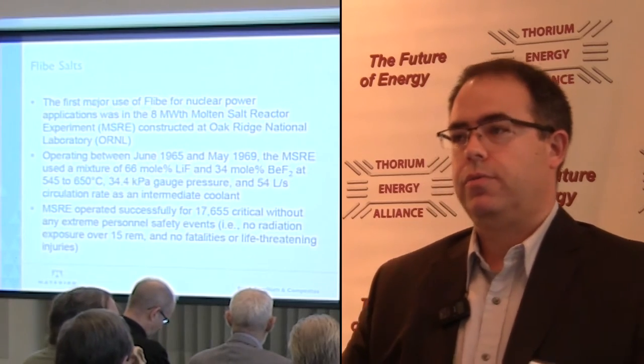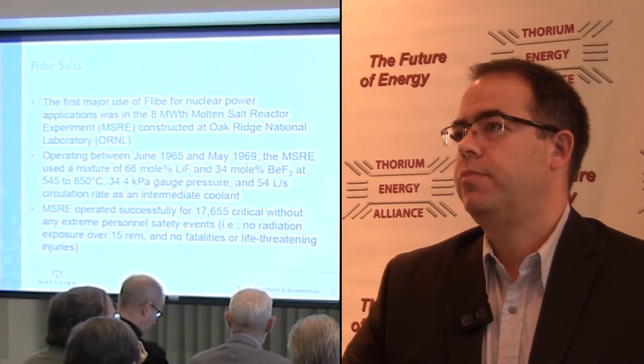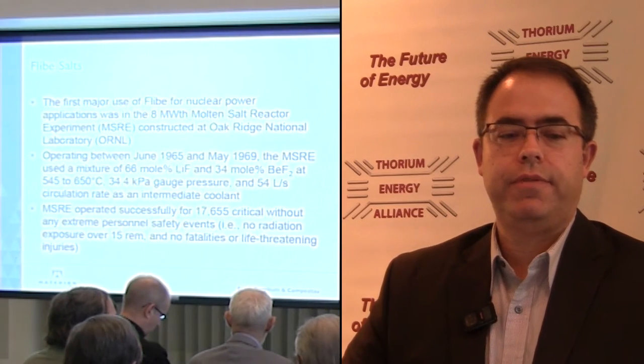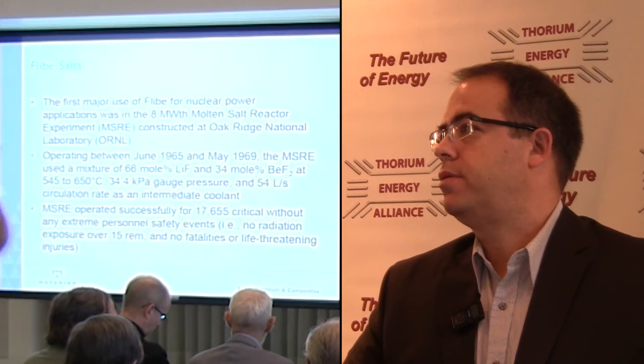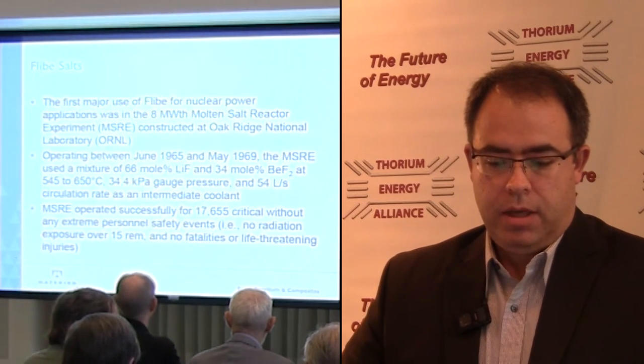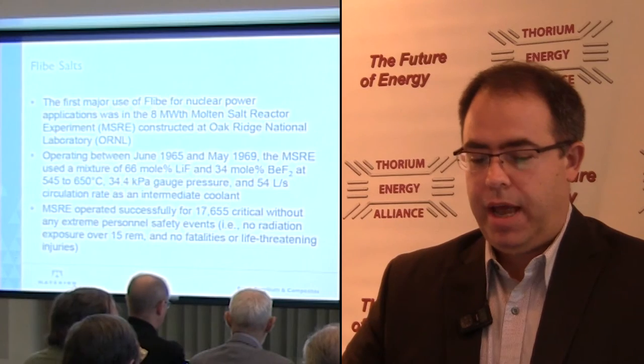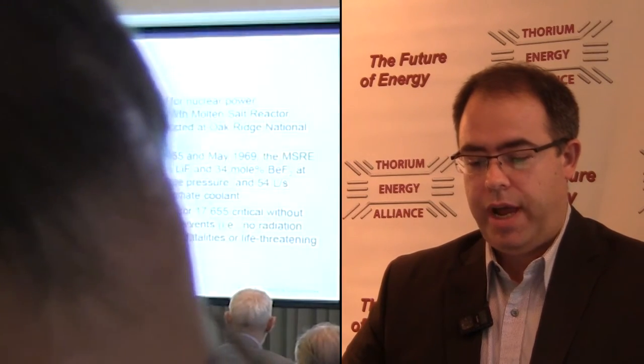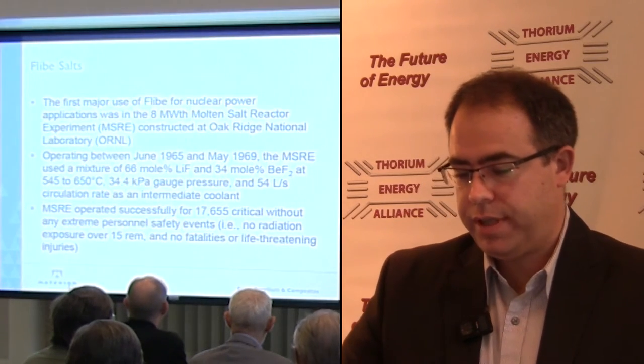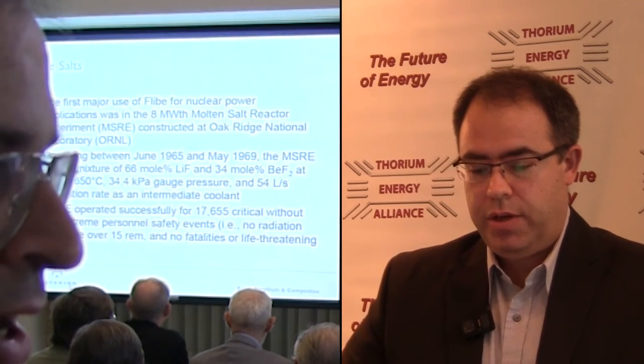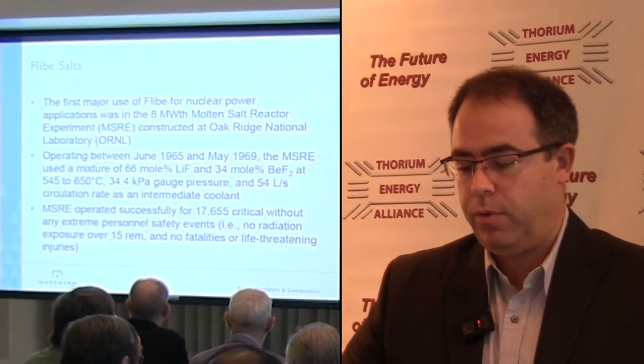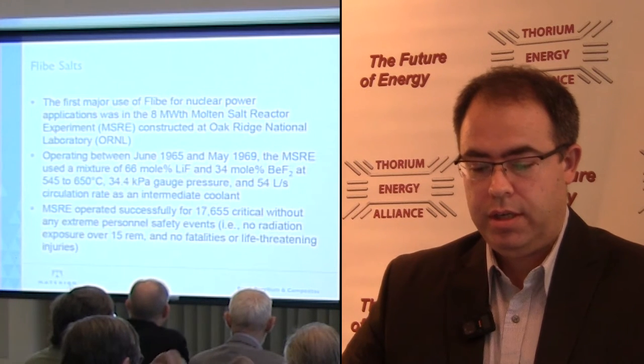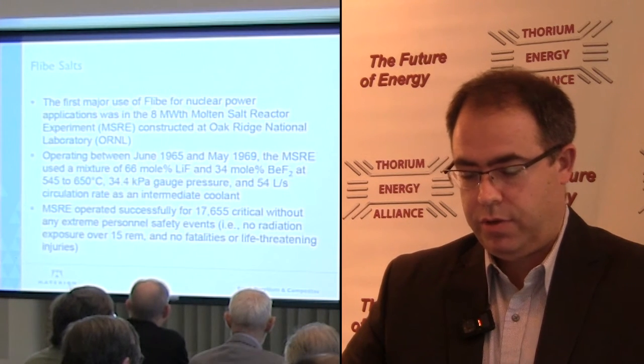So FLiBe salts, what's FLiBe? FLiBe is just a name, an acronym that's been used since the molten salt reactor era to define beryllium fluoride, lithium fluoride salts. And you guys know this better than me, an 8-megawatt thermal molten salt reactor built by Oak Ridge National Lab worked between '65 and '69. It used mostly 66 molar percent lithium fluoride with 34 molar percent beryllium fluoride. Those temperature ranges and those rates.